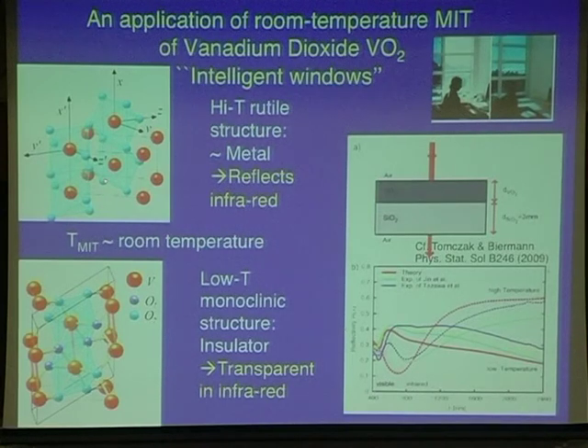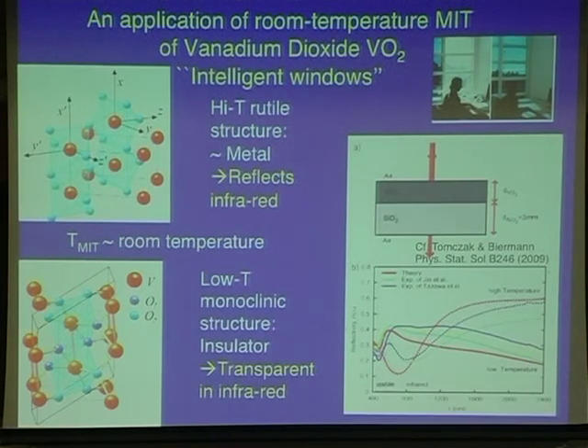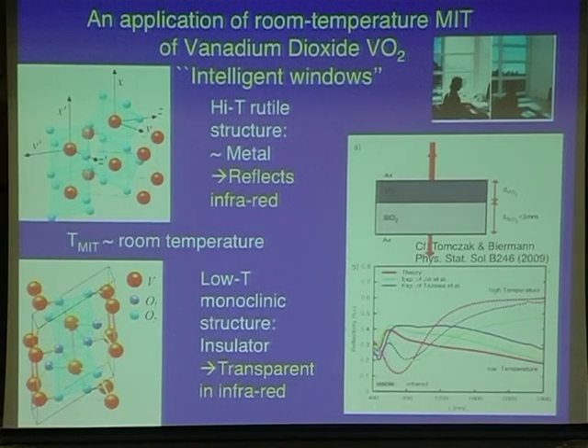At high temperature, it's a metal, above about 68 Celsius. At low temperature, it's an insulator. So you can actually use this to coat windows and climate control your room. This is actually something that is, in fact, fabricated by companies like Saint-Gobain in France. At high temperature, when it's warm outside, this material will reflect in the infrared, so you will avoid your room heating too much, while at low temperature, you will let in the warm sunlight into your room. It's not so intelligent, windows, but for a window, it's kind of an intelligent behavior.